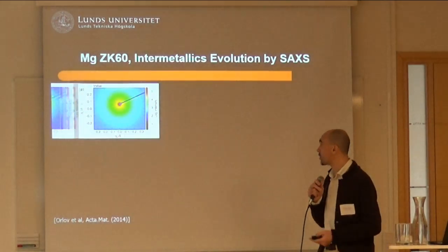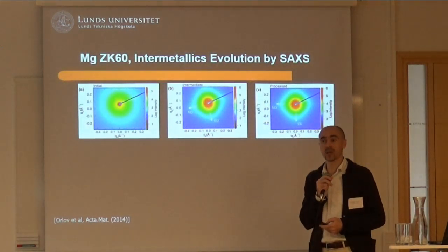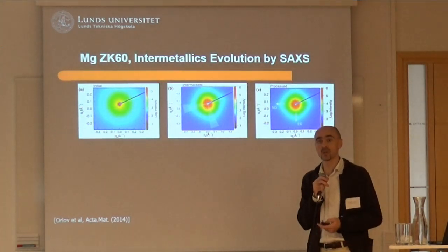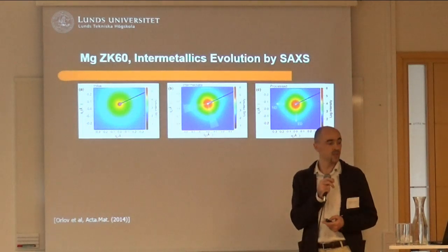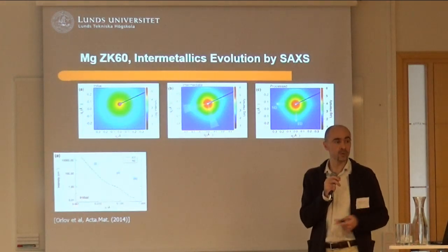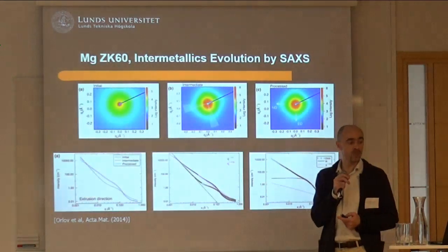Then we found with the synchrotron-based techniques like small angle scattering, statistically we do have plenty of them. So they are a significant fraction or contributor to the strength of your materials.